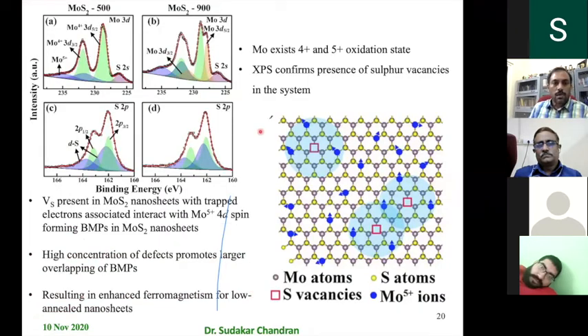Of course, our interest was to study what happens to the magnetic properties. In these compounds, the molybdenum exists in both 4+ and 5+ oxidation states. The 5+ comes because of the defects present in the edges, point defects, and so on. And the 500 degrees Celsius sample has a large concentration of these defects. Whenever you have these kinds of defects, there could be trapped charge carriers. And since molybdenum can have a single unpaired electron in the 5+ state, because it's an oxidized state, the single spin associated with it can interact with these defect sites with the trapped charges, and that forms magnetic polarons. When you have a sufficient concentration of Mo5+ and the defects, there could be overlap of the magnetic polarons, and you may get the magnetic properties enabled.